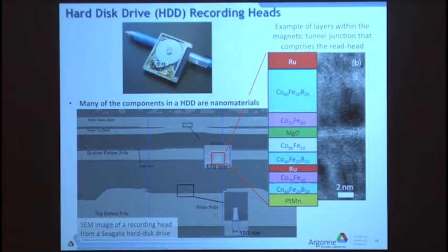Part of that does the writing and part of it does the reading. I'm not going to go into great detail, but there's something in here that we can't even see, so we've blown it up here. 170 nanometers across is the read head. It's an incredibly complicated structure. It has all these different layers in it: cobalt, iron, boron alloy, cobalt with iron, magnesium oxide here. The whole way that this works is the signal across this layer here. This is a high-resolution transmission electron microscope image of that structure, so you can see all the atoms in there.